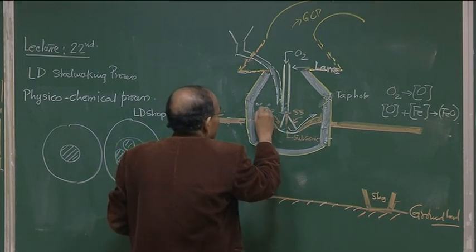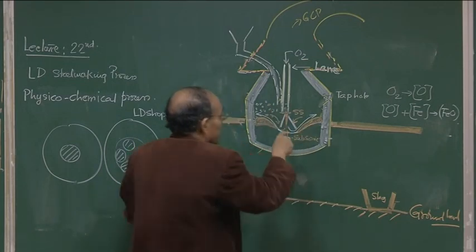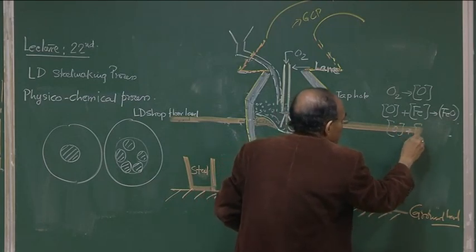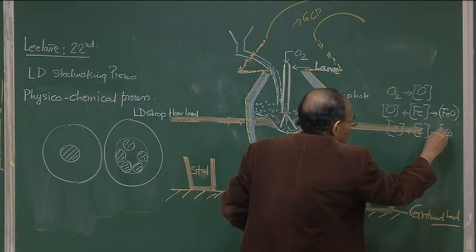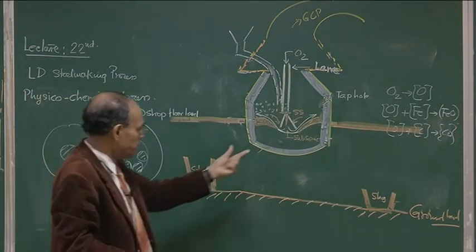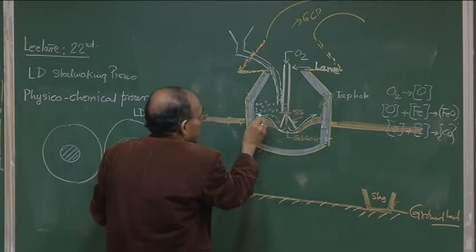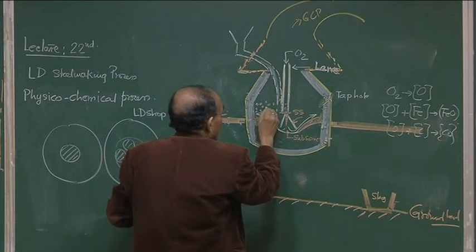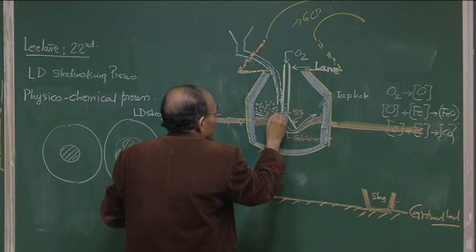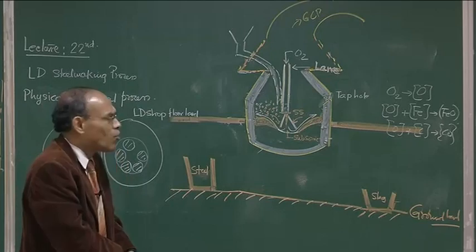So they will have a flight time here. Similarly, with oxygen plus carbon, carbon dioxide is not important. Carbon dioxide cannot form at that temperature, and carbon monoxide is evolving. Gas is evolving, and there are droplets. I am just drawing on one side. There are droplets of slag and droplets of metal, the red ones. They are going to be ejected. They are not going to be discrete; they are going to be intimately mixed slag-metal droplets.